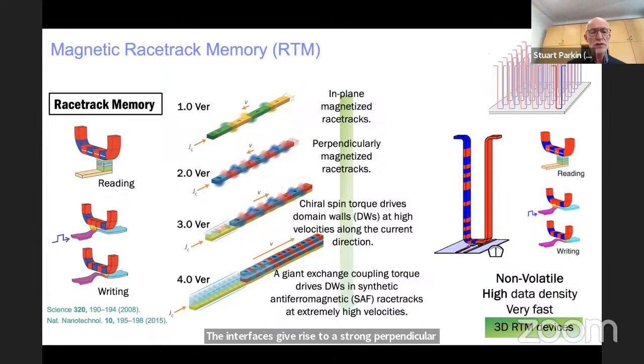So these shrink the domain walls, and we demonstrated that we could move these domain walls very similarly as in the cobalt-nickel alloys, at roughly the same speed, about 100 meters per second, for useful current densities. So in version 3.0, we built the racetrack, the perpendicularly magnetized racetrack, on top of a layer of platinum, and it had been shown by others that this platinum gives rise to a strong spin Hall effect. Well, we actually demonstrated that the strong spin Hall effect moves the domain walls at much higher speeds, about 3 times higher than in versions 1 and 2, about 300 meters per second.